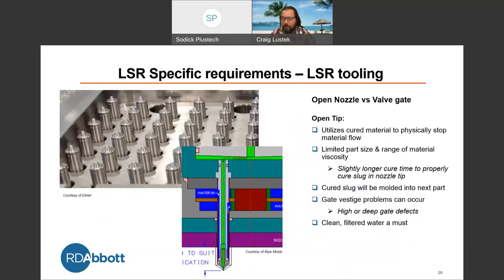We talked about the open nozzle versus valve gate design. Here's an example of an open nozzle. So the open nozzle design actually utilizes cured material to physically stop the material flow. So this limits your part size and the ranges of viscosity. As different viscosities, different part sizes, this can change your total cycle time. The cured slug, unfortunately, is going to be molded into your next part. So this is something you have to think about.